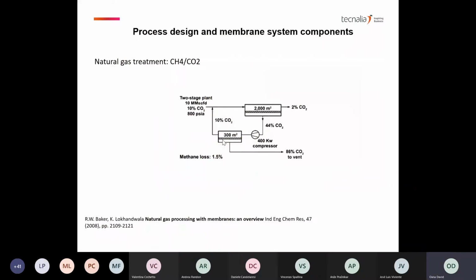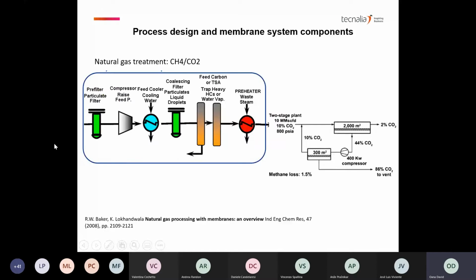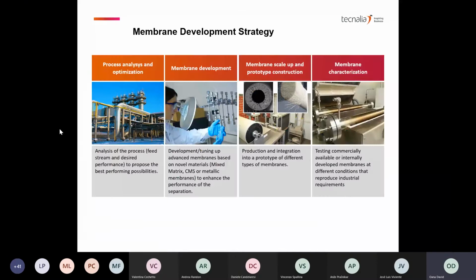And what is very important also is process design and membrane system components. Here I give an example for natural gas treatment. It's not separated in one single unit. There is a second unit that recirculates the permeate from the first unit in order to have a very low methane loss for the whole separation. And then what is also important is the pretreatment of the gases. We do not want streams that reach the membranes to contain particles, water droplets, heavy hydrocarbons, or other heavy impurities.